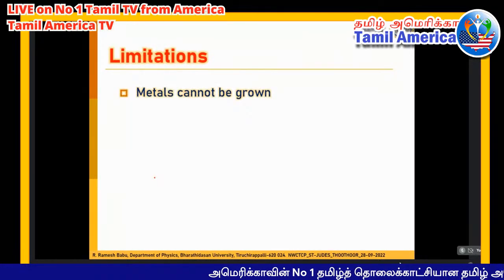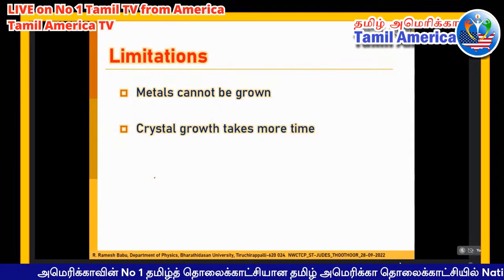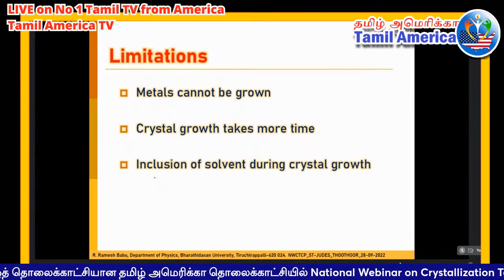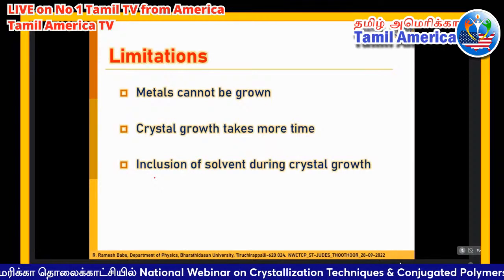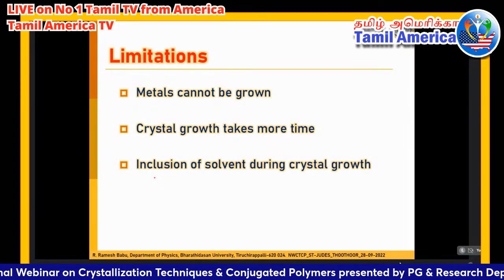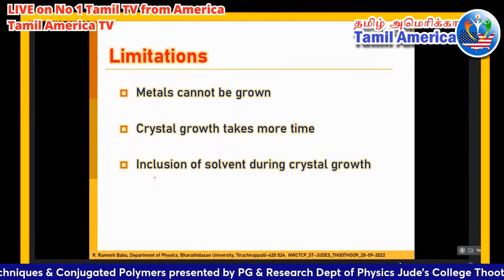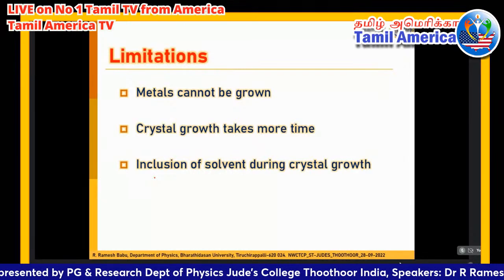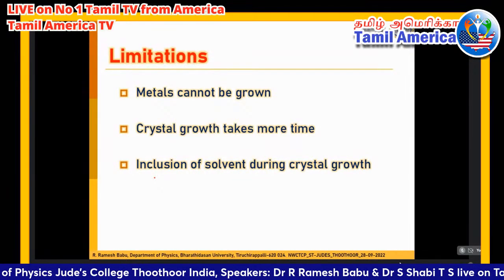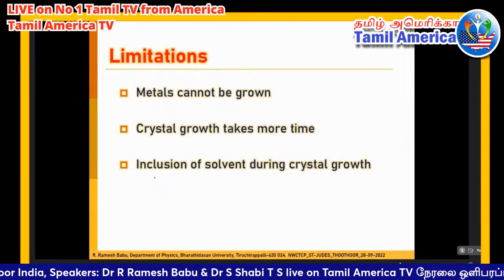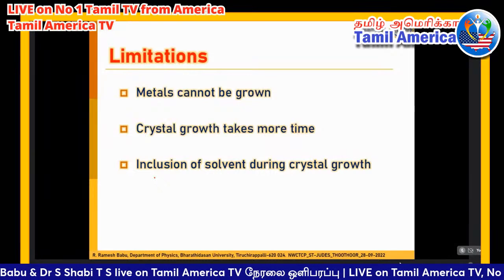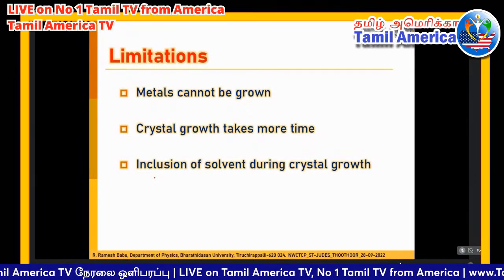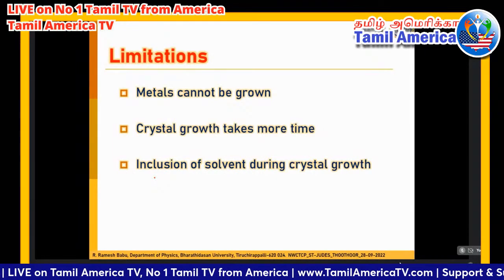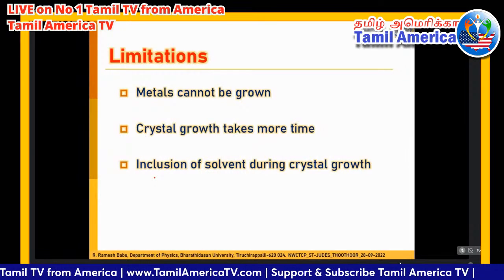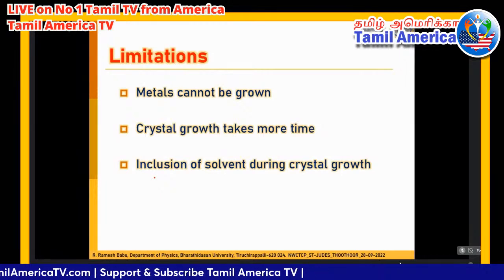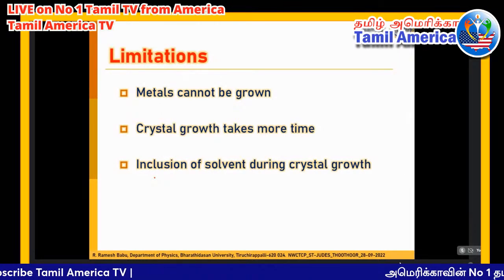The limitations of these solution growth techniques: metals cannot be grown by this technique. Crystal growth takes more time when compared to melt growth techniques. Sometimes, not in all cases, the inclusion of solvent is possible. Means, I want to grow a single crystal of X, sometimes using a solvent like water. Sometimes these water molecules may be included into the X, that is our material. Therefore, we can end up with X·H2O or X·2H2O, hydrated materials, which is not useful for our purpose. Our aim is to grow material like X, but we end up with X·H2O or X·2H2O, like hydrated materials.